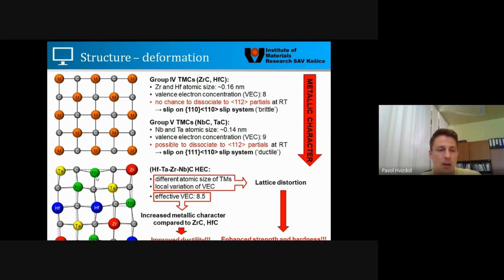In case of high entropy carbides, specifically the hafnium, tantalum, zirconium, niobium carbide, we have a mixture of them. So we have different atomic sizes of the transition metals from which it builds up. We have local variation of the valence electron concentration, and this kind of mixture causes lattice distortion. And this lattice distortion acts as a barrier for the movement of dislocations, so we expect enhanced hardness and strength, and this is what we experimentally verified.